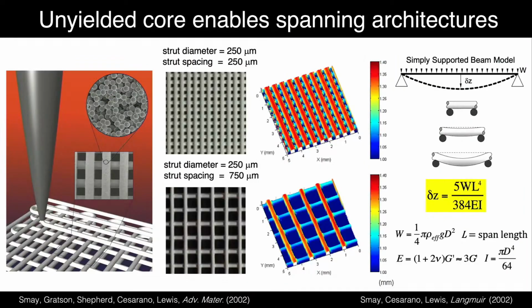So we then did some work to show that because of this ability to engineer the elastic moduli, we could span very large gaps, and we could tailor that with respect to the value of the shear modulus, the particle-particle interactions. And we showed that then taking these inks, we could make these nice, beautiful lattices. And as I said, this is very old work, but you can see the uniformity of these features even as they're spanning very large gaps, right? This is just a surface profilometry scan. They're all very nicely uniform.